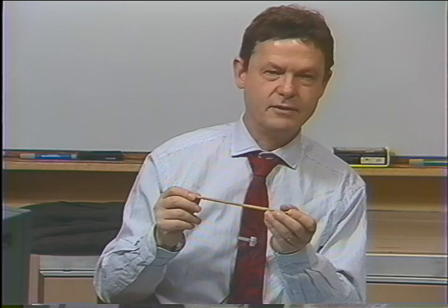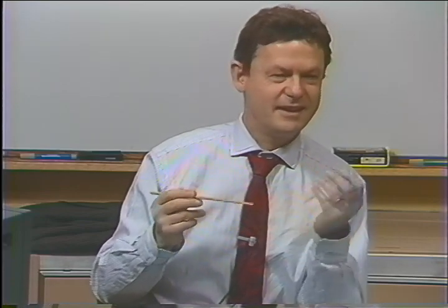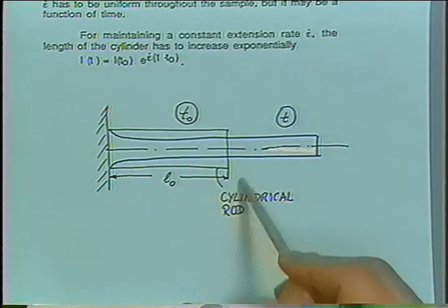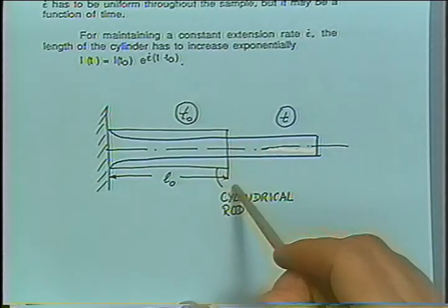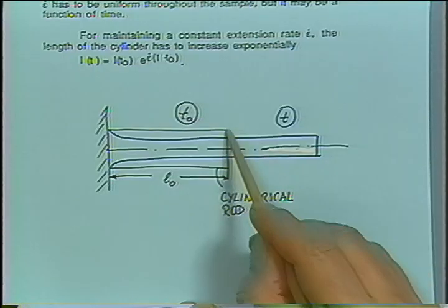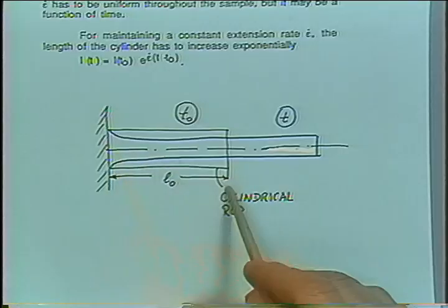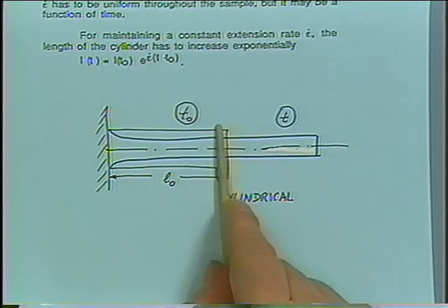simply to have this type of function in a drive. And for overcoming the problem, Meissner in Germany at the BASF stretched a fiber like this by mounting rotors here, or a pair of rollers here. He noted that the velocity at one position away from the stagnation point has to be constant.